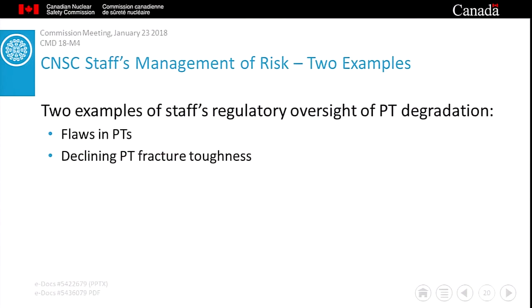To illustrate how CNSC staff's oversight process works, I'd like to take a closer look at two examples. First, a form of degradation where CNSC requirements oblige the licensee to prepare a fitness for service assessment based on in-service inspection data. So for this example, we'll look at pressure tube flaws. Second, a mechanism that by its nature cannot be measured in service, and that's fracture toughness. As we'll see in a few minutes, licensees use predicted fracture toughness values as a basis for core-wide assessments of the risk of operating uninspected pressure tubes.